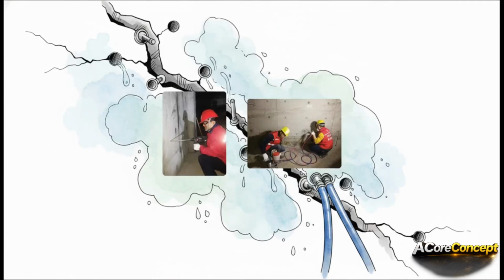Now, for the actual on-site administration. The maintenance team first drills insertion holes directly into the structural failure, like an active crack in a concrete wall. They install packers tightly into those holes, attach the pressure hoses, and then actively force the expanding polymer deep into the hidden void. The second that liquid hits any moisture inside the wall, it expands, actively chasing the water out and permanently sealing the pathway. It's really something to see in action.